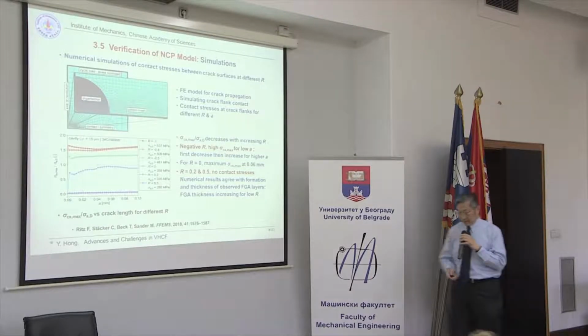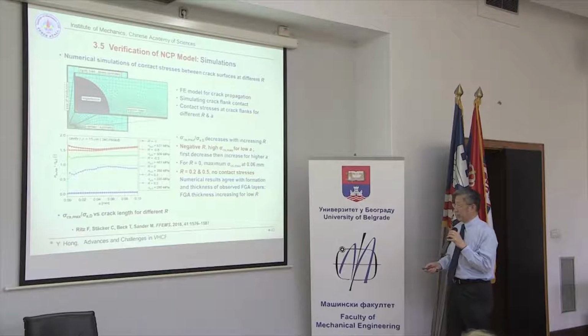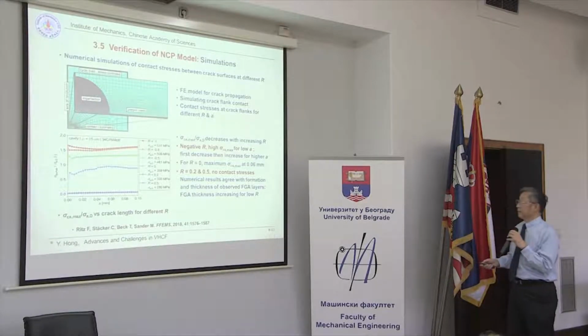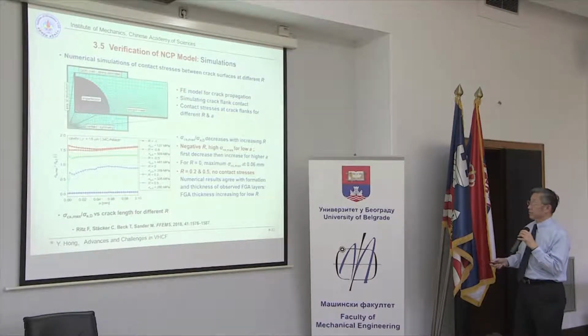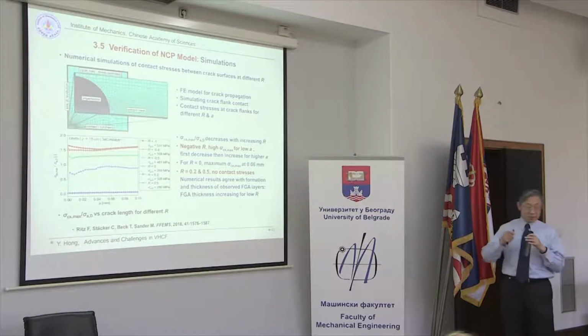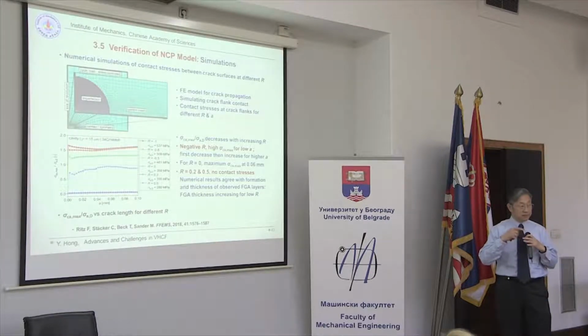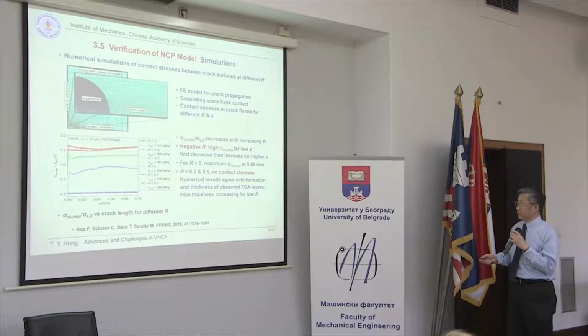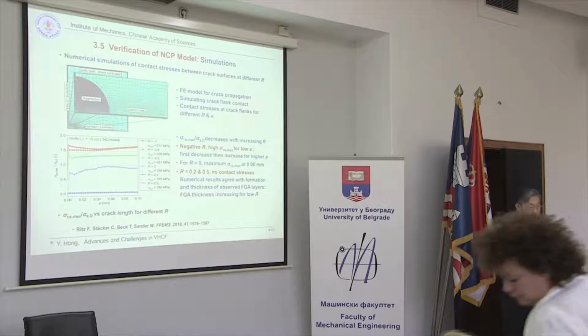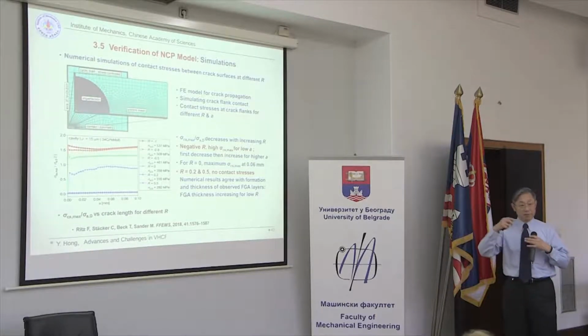And this is a simulation result given by two German research groups. One is Professor Beck, the other is Professor Sander. Their simulation result shows that for different stress ratios, here the positive stress ratio like 0.5 has no contacting stress at the surfaces. And for negative stress ratios like -1 and -0.8, they have quite a large value of contacting stress. So this is also a result to support this type of process, the contacting between crack surfaces after crack initiation.